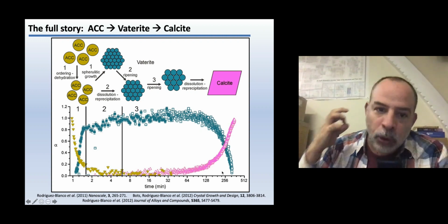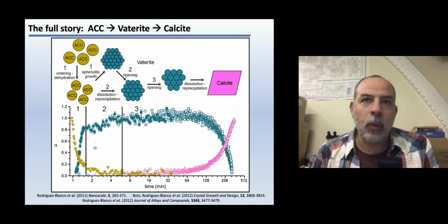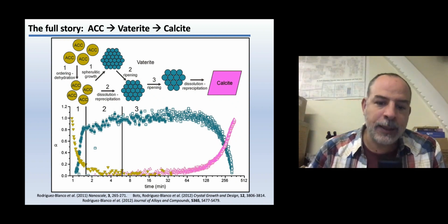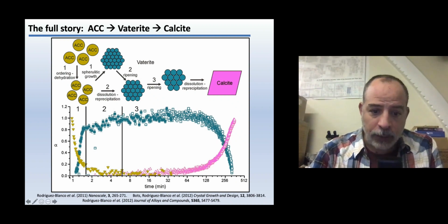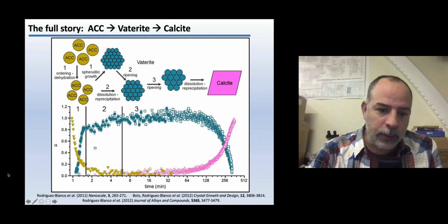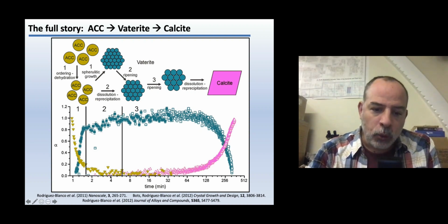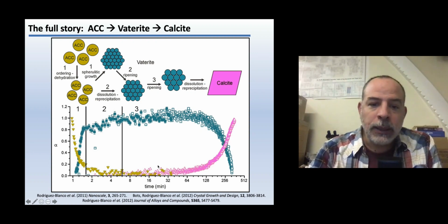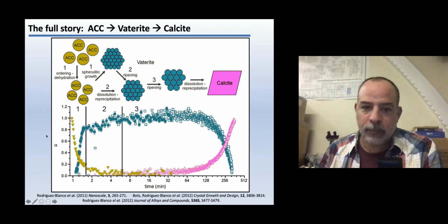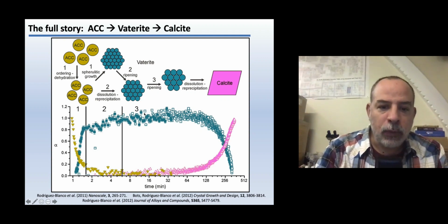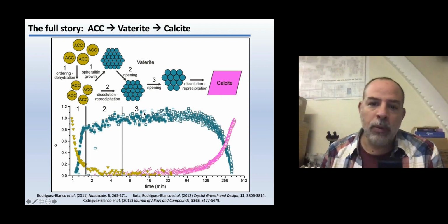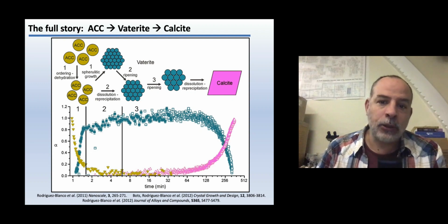But it would be impossible to obtain this picture without using synchrotron-based techniques, because you can see here time, and this time is not linear, it's logarithmic, and you see here 1, 2, 4, 8 minutes. So in 10 minutes more or less, half of the reaction has happened. Vaterite is fully formed. That would be much more complicated to follow using non-synchrotron-based techniques.